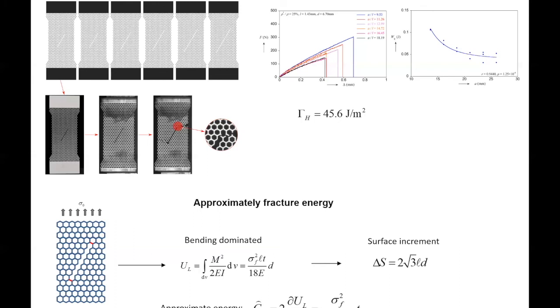So if there is a boundary effect, or if after fracture, remember we removed one ligament, right? And you see the stress state. Just because one ligament has higher stress, if it has 3% higher stress, in the numerical model this 3% makes a difference. In a real experiment that will not always be the case, right? So you have all these variations, and they're going to come into play.